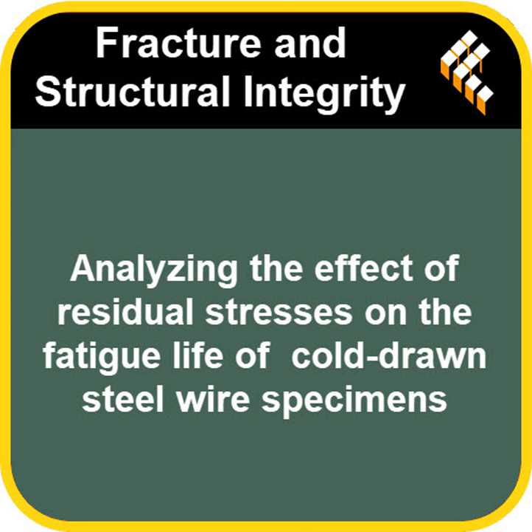They noted that for parts that get yielded quite a bit in this process, the residual stresses right at the border between the elastic part and the plastic part, that stress can actually be higher than the stress right on the outer surface. Isn't that counterintuitive? You'd think the surface takes the biggest hit. Right. But mechanically, that transition zone, the elastic plastic border, it can lock in more intense stress. It tells you something about how stresses redistribute internally when you yield a material.